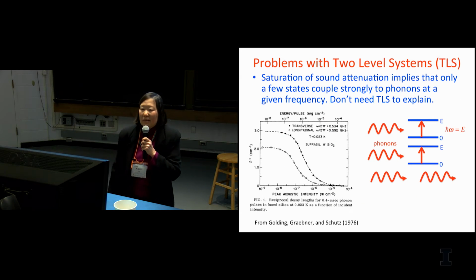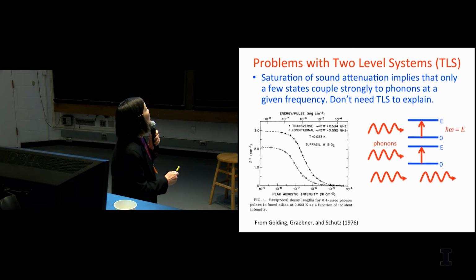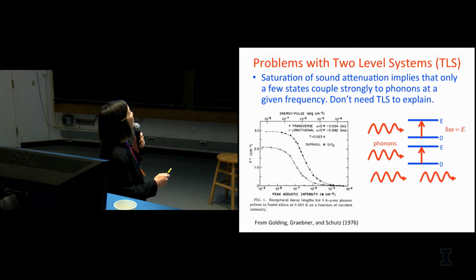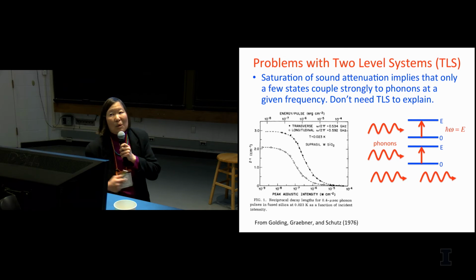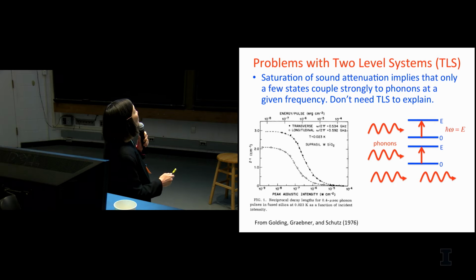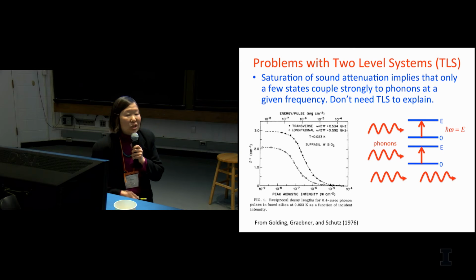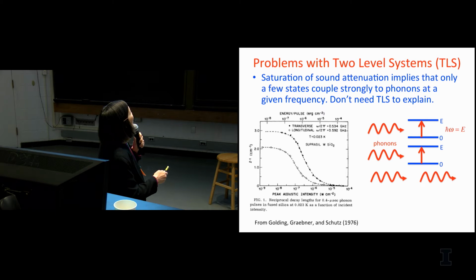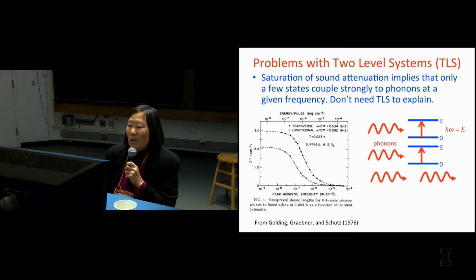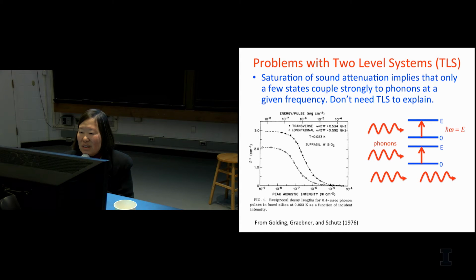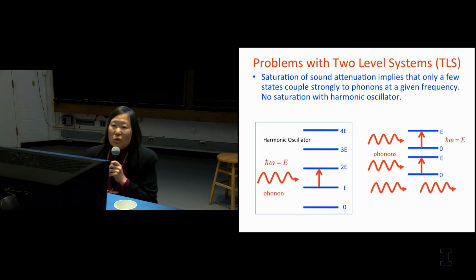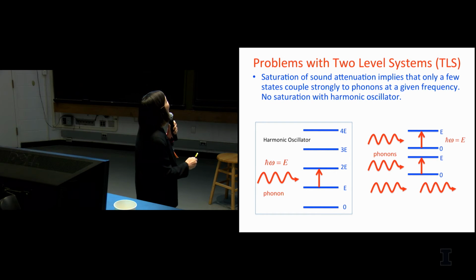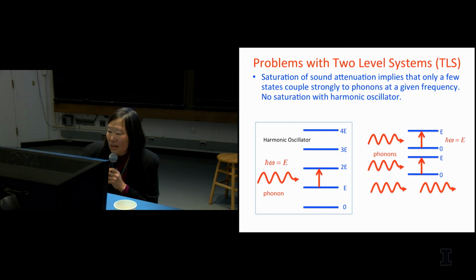Another example would be sound attenuation. The idea here is that you're sending in some phonons. The ones that match the energy splitting are going to be absorbed. That will attenuate your sound. But if you crank up the intensity and send in more and more phonons, eventually you outnumber the two-level systems at that energy, and these excess phonons get through scot-free. So if you plot the sound attenuation versus log of the intensity, you see attenuation decreasing. So again, you don't need two-level systems. You just need to say you have a few states that strongly couple to the phonons at a given frequency, and you don't have harmonic oscillators.